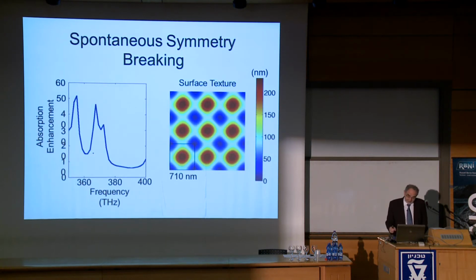So we approach this with periodic boundary conditions, and we try to solve for what is the optimum shape. And you can imagine that maybe it's a square array like what I've shown, maybe a square photonic crystal like this. And we've used a mathematical approach for inverse solutions. And you need a figure of merit. And the figure of merit is by how much you increase the absorption. I see my numbers here are a little bit messed up, but this is 10, 20, and 30 times enhancement.